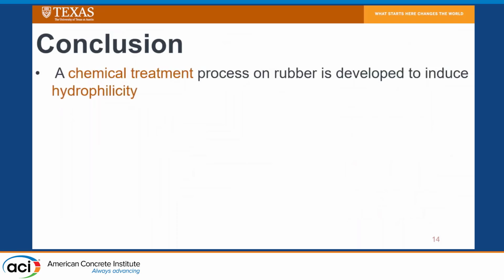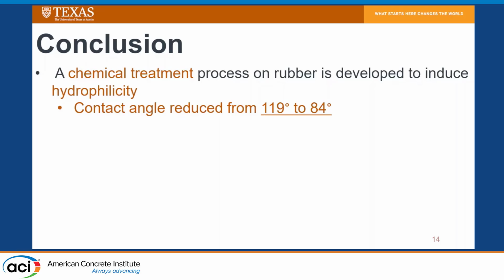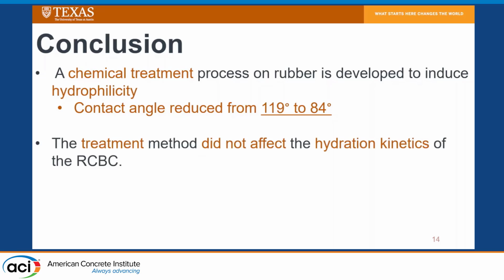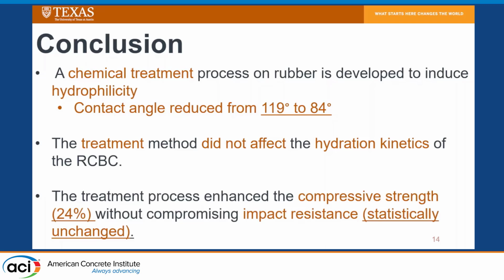So in conclusion, we found that we were able to develop a chemical treatment process that is suitable for cementitious composite matrix. And the main goal, which was to induce hydrophilicity, was achieved. We were able to reduce this from a hydrophobic nature to a hydrophilic nature. We saw that the treatment method did not impact hydration kinetics. And we also saw that we were able to achieve our goal of enhancing the compressive strength, and we did not compromise our impact resistance.